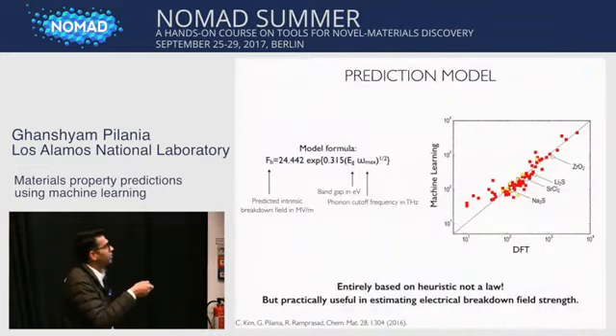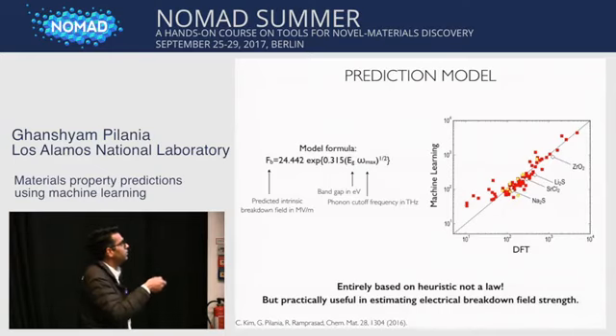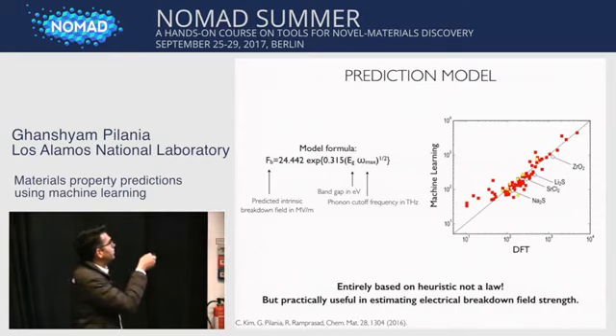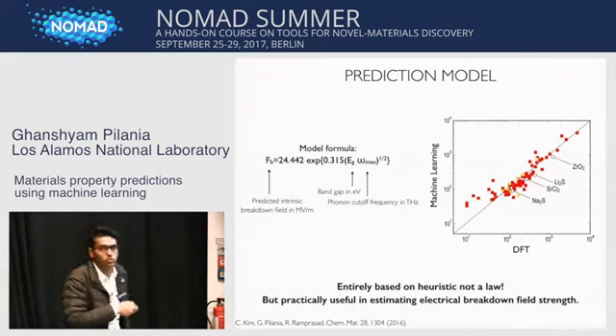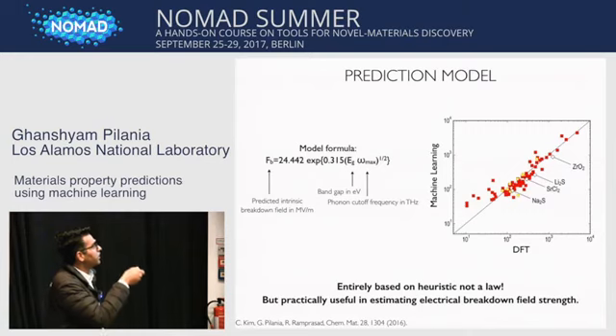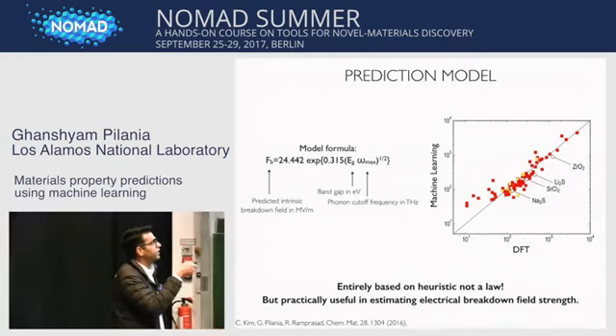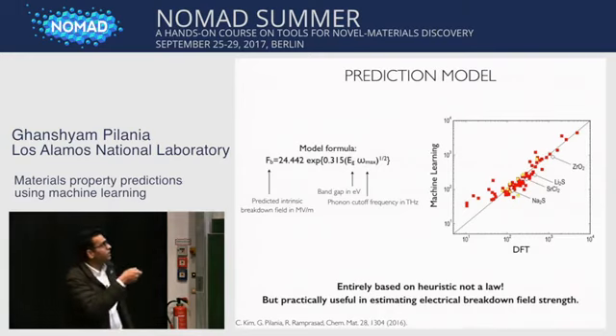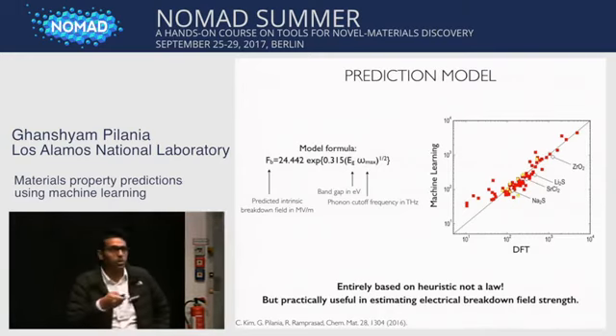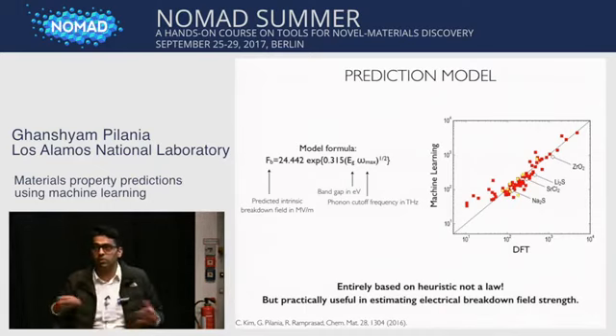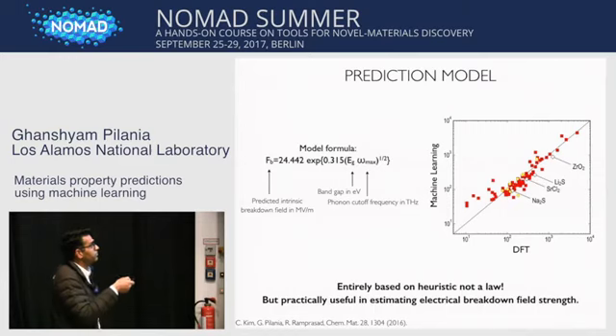So we take that feature and we compare it with the predictions made with DFT, so that's the correlation. On the x-axis we have DFT predictions, the DFT computed value of the breakdown, and on the y-axis we have machine learning predictions, which is given by our machine learning analytical form, expressing breakdown field as a function of band gap and phonon cutoff frequency. So that's the machine learning prediction. In red it's the training set, yellow is the test set, and then white diamonds are other compounds which were not part of the original binary octet. So we wanted to try it on something new and see how it works out, and it seemed to be working well.